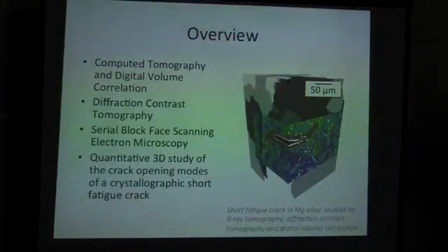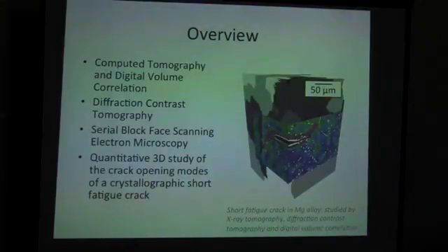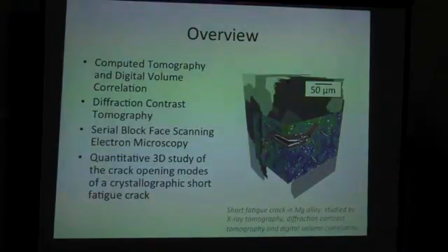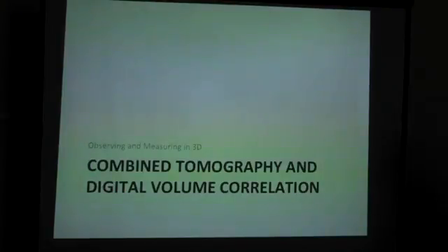We've worked with magnesium. We've done it for several reasons. First of all, it's low attenuation, so it's great for X-ray techniques. It's got a nice big grain size. It cracks in an interesting way, and particularly the high temperature magnesium alloys, which alloy with things like neodymium and other rare earths, give you great contrast for tomographic techniques, which gives you speckle and features within the microstructure. I'll come back to this image towards the end.